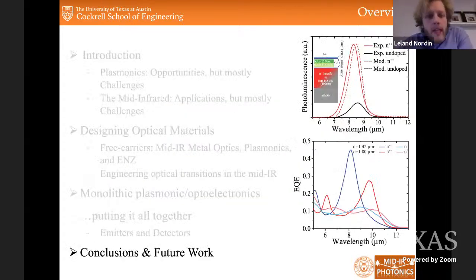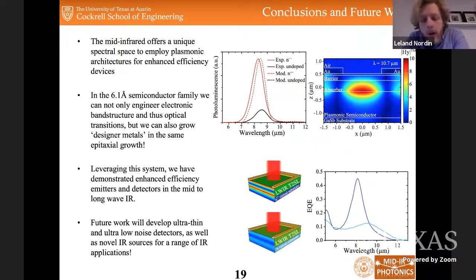So now I'm going to conclude my talk. The mid-infrared is an especially exciting wavelength range to work with plasmonics because we're able to monolithically and seamlessly integrate these plasmonic materials with these semiconductor active regions. And we've been able to show enhanced efficiency, not only in terms of emission, but also absorption. We're very lucky because the 6.1 semiconductor family, indium arsenide, aluminum antimonide, gallium antimonide, we're able to integrate and grow doped semiconductors in the 6.1 semiconductor family and these emitters. Doing so, we've been able to demonstrate enhanced emission, we've been able to demonstrate enhanced detection, and we've been able to do so in ultra-thin absorber regions, beating state-of-the-art infrared detectors.